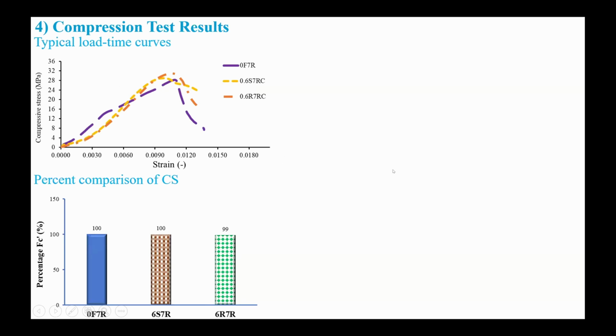The compression test results: we did draw stress strain curves, and from the stress strain curves, we also compared the compressive strength, and you can see there was not much significant effect on the compressive strength. And with the recycled steel fibers, this compressive strength got decreased. This is because most of the literature review also concluded that by using a high percentage of fiber, almost more than 0.5%, the compressive strength was not much improved, and a decline was also reported by different authors.